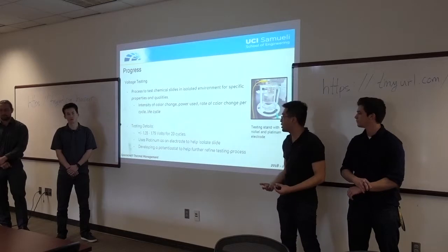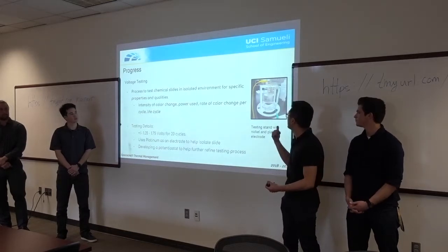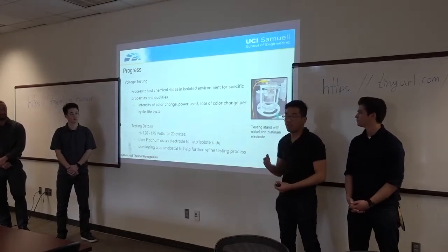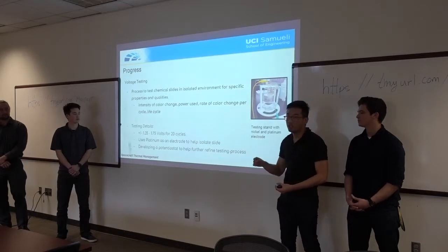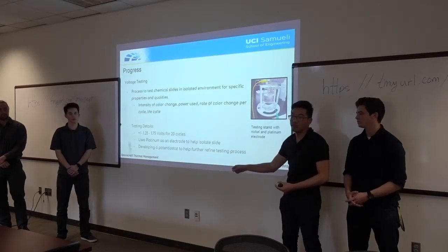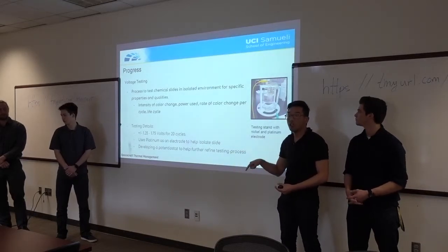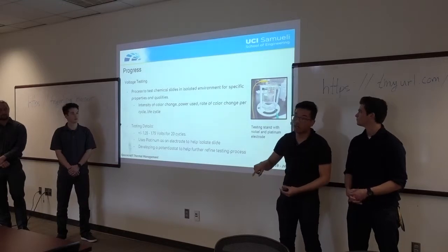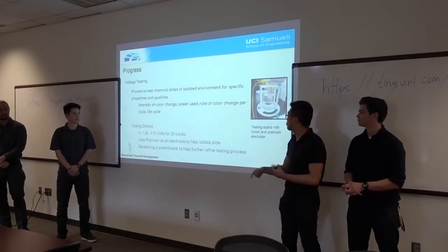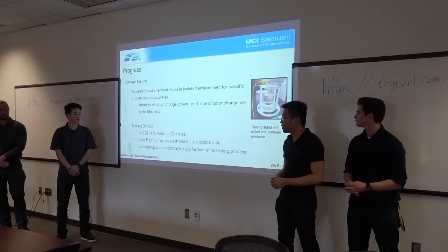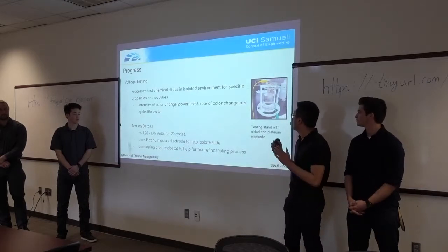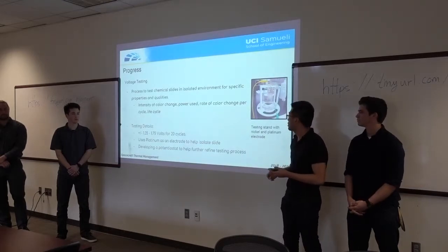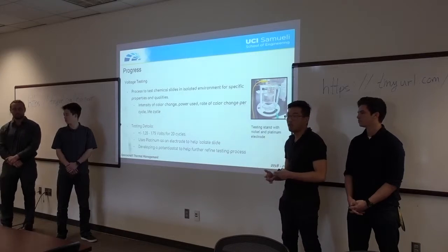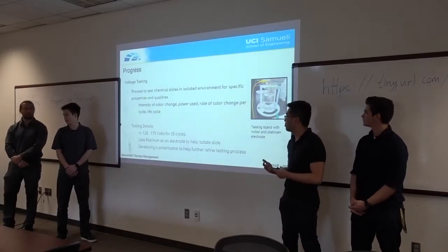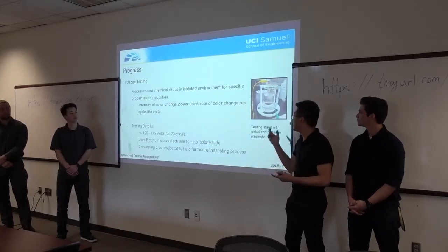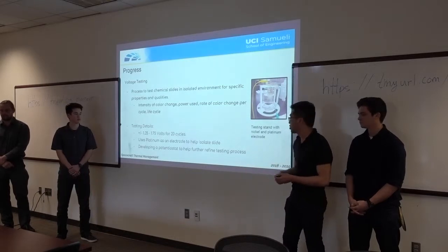So what we do is we test these slides at 1.25 through 1.75 volts for 20 cycles. We'll flip the voltages back and forth, changing the currents. So it'll alternate from changing to dark, changing to bright, to a brighter color. We use platinum as the electrode because the chemical properties of platinum work better than most other metals in terms of transporting electrons.